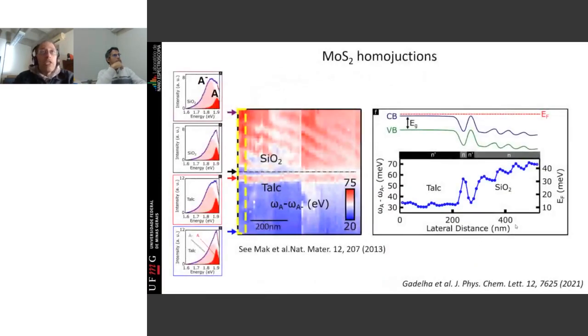And if I now image the difference in frequency between these two excitonic responses, this was also established in 2013 by some other fellows here. This is also a way of you measuring doping in this semiconductor MoS2. And again, if you look here, it's blue, red, blue, red. Again, you are measuring the depletion region, but you also have some sort of oscillations that you nicely see happening here, okay? And again, all this information is now obtained optically in the nano optics regime, because you can scan the nano antenna.